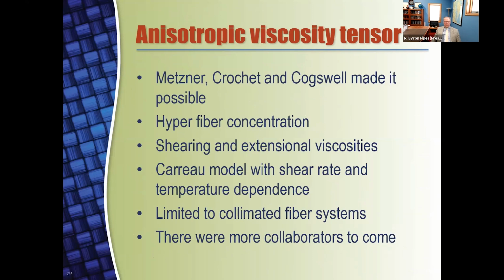Well, I make a comment here and maybe take a moment and say, how did this all happen? Well, were it not for Metzner, Crochet, and Cogswell, it wouldn't have happened. But it did, and it does allow us to consider hyper fiber concentration. It allows us to predict all of the viscosity, shearing and extensional. It gives us the shear rate characteristics and dependence and temperature. However, it's limited to collimated fiber systems. And so there needed to be more to come on this subject. By the way, this was generally completed in the decade of the 90s.